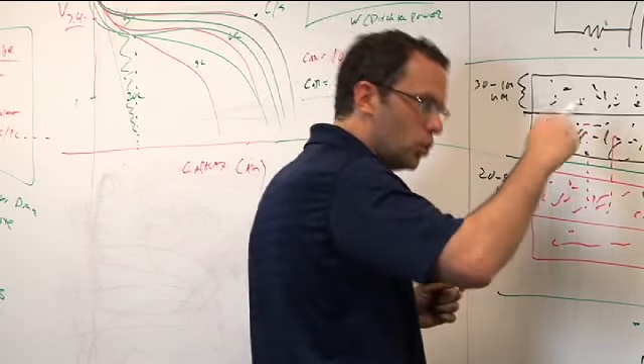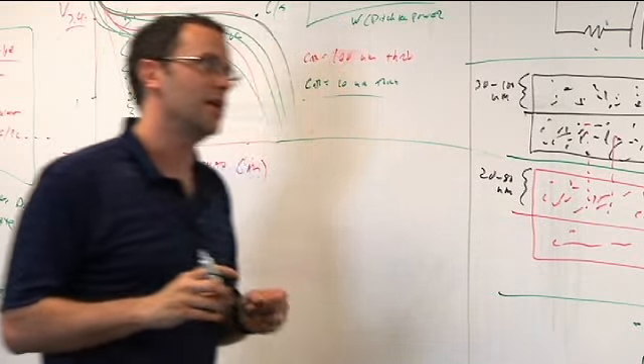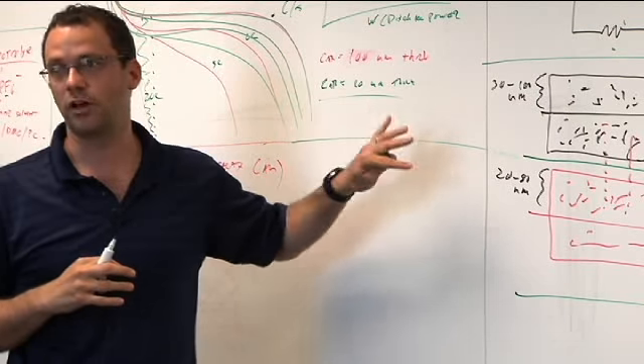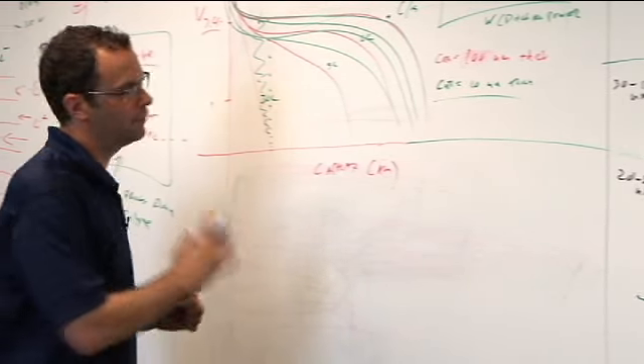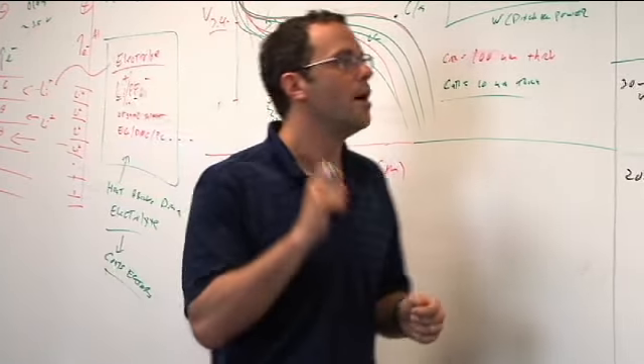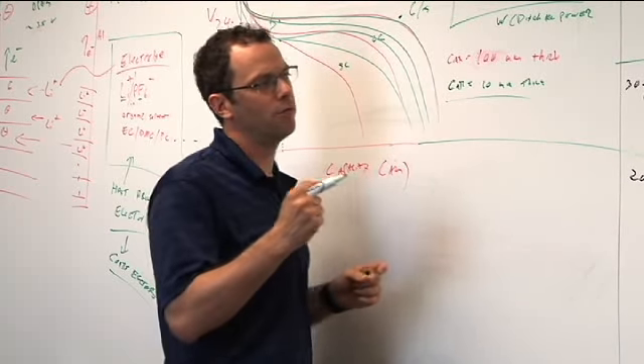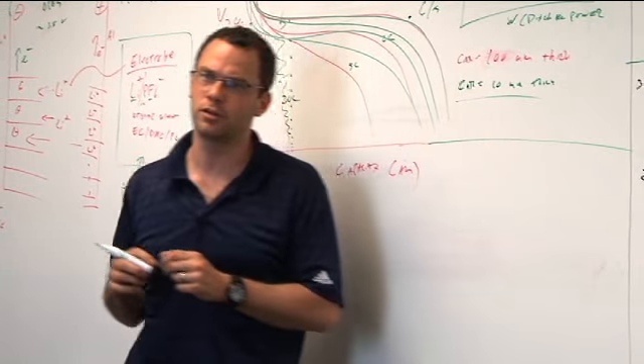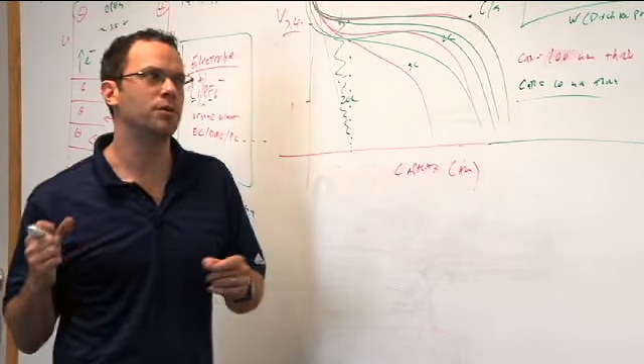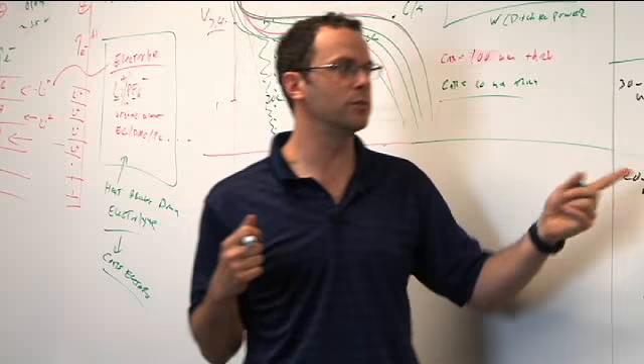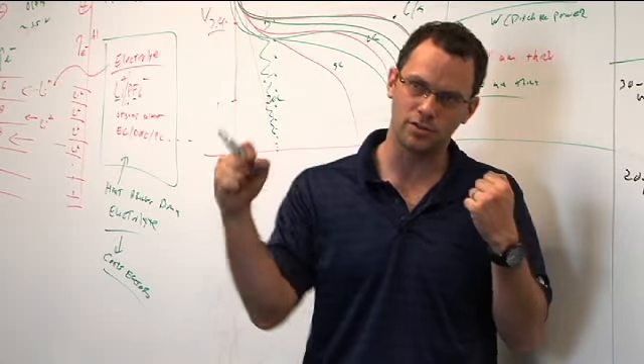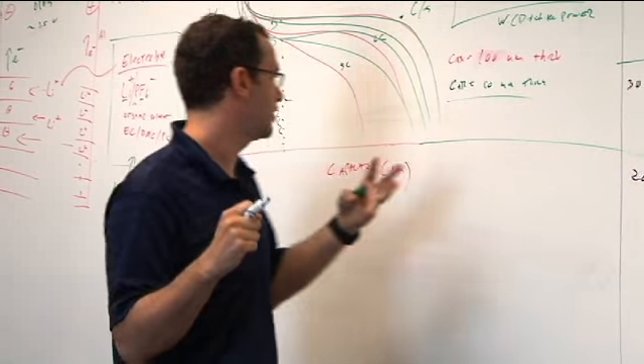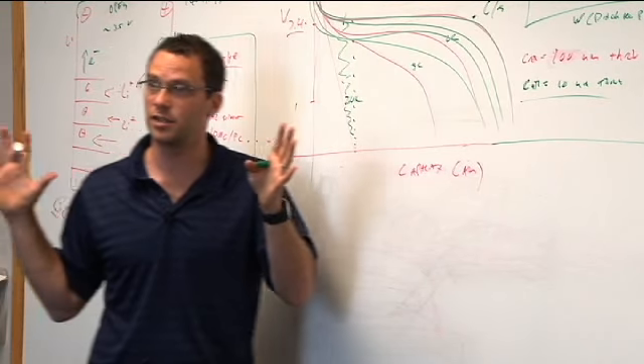And it turns out that by doing that, and it's very specific to every individual cell thickness, cell geometry, thermal management approach, all that, you have to figure out what it is for individual cells. But there are pulse regimens for both charging and discharging that allow for, on average, a more efficient use of the materials than if you were doing a constant current. It has to do with the fact that the pulse allows you to increase the local heat a little bit to enhance the diffusivity without really impacting the long-term heat exposure, if that makes any sense at all.